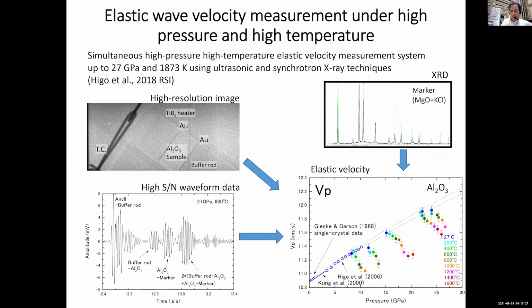Also, this is an example of an elastic wave velocity experiment. In this beamline, we use a high resolution X-ray absorption image to measure the sample length, and energy dispersive XRD data is used to estimate density. A very high resolution ultrasonic measurement system gives the travel time of the ultrasonic wave. These three data sets can estimate the elastic velocity up to the topmost lower mantle conditions.